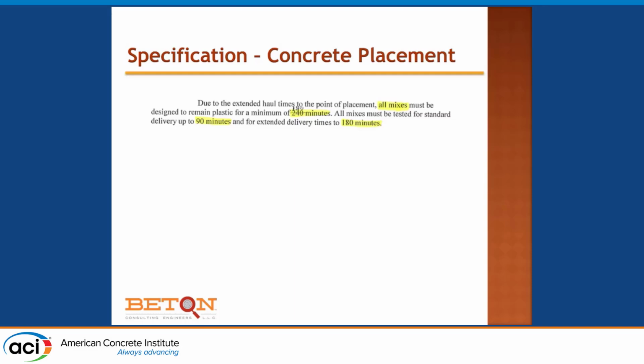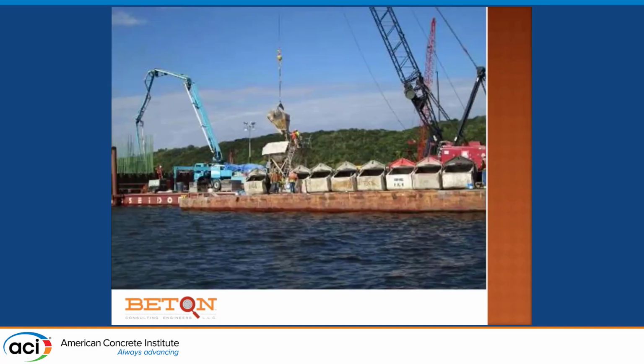This is my favorite. Not only do you have to have 4,000 psi in 18 hours, your concrete has to be workable for 240 minutes. You see some stroke there, 240, written over 180. 180 minutes. So why would you want, with the St. Croix, the crossing is just outside of metropolitan Minneapolis, why would you want something to set that long? And that's because of the construction method that had been selected.